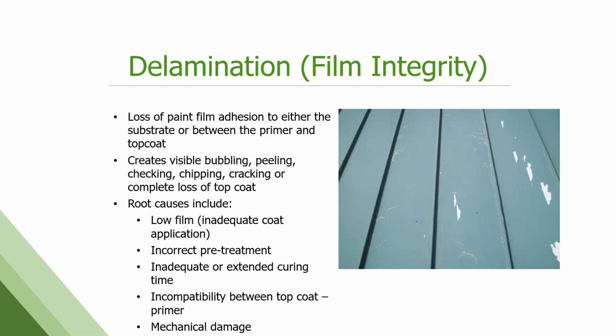Delamination is another big one, and this is probably the toughest failure we see as far as determining why, because there can be a lot of reasons for it out in the field. So this is a loss of the paint film, either between the top coat and the primer, or all the way down to the substrate, and it can present in a lot of ways. It can be bubbling of the paint, peeling, chipping, cracking, complete loss of top coat. It may be small, it may be big.